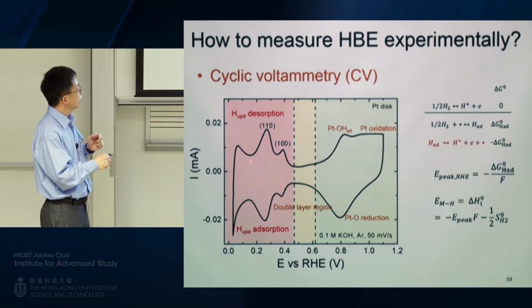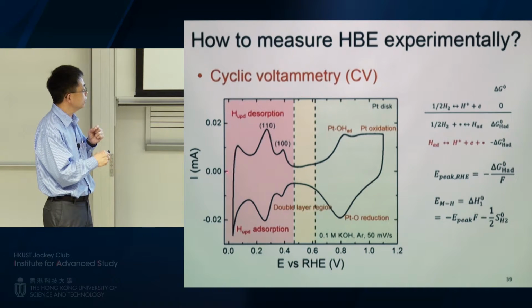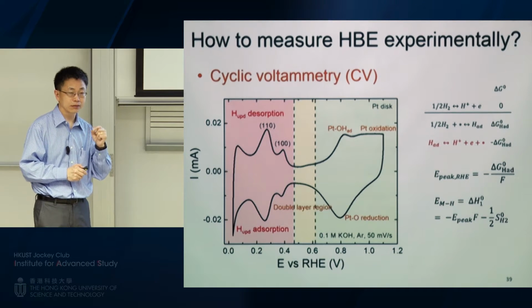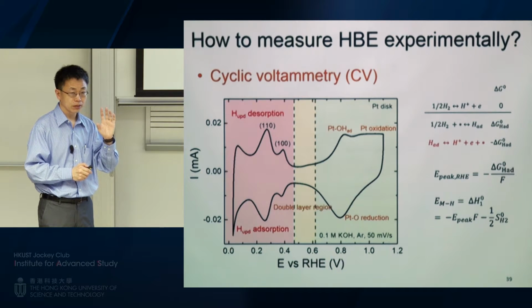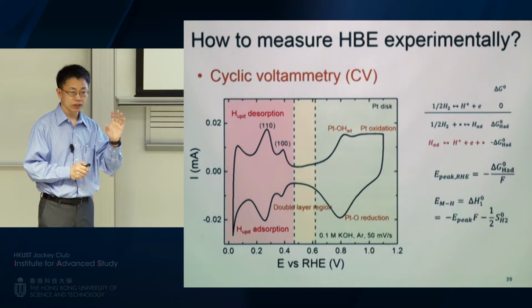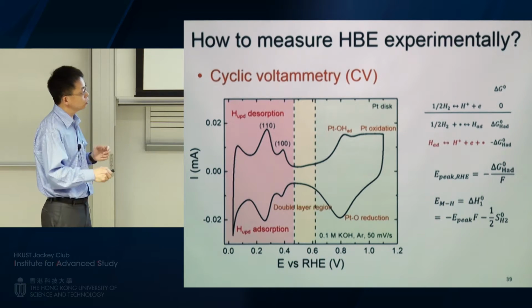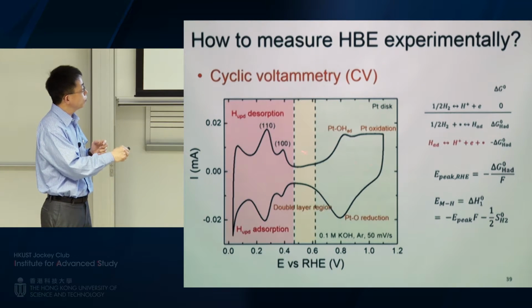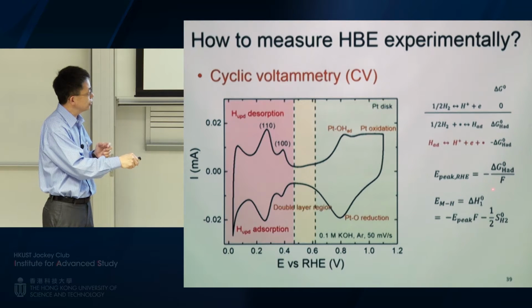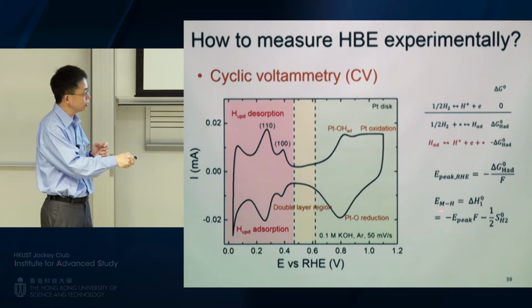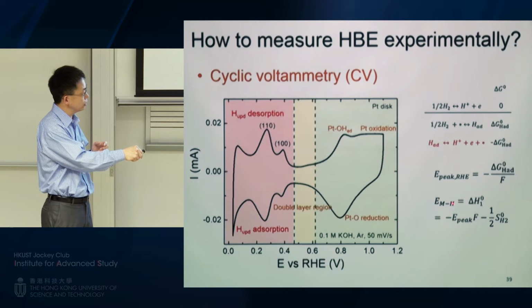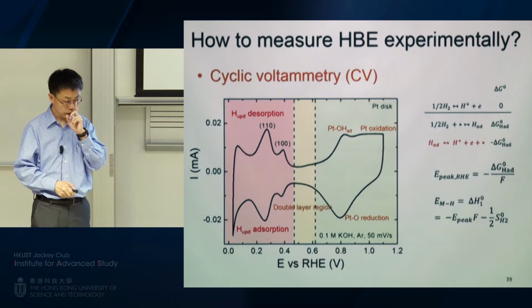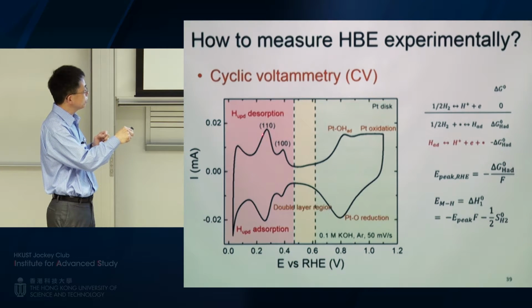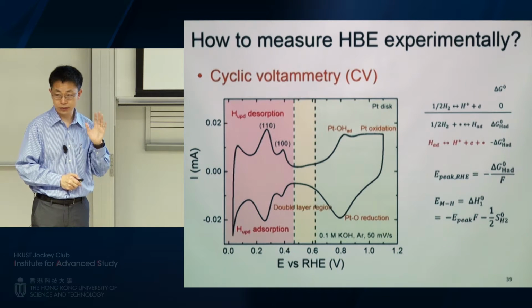What I want to say is, it has been known for a long, long time in the electrochemistry community that the peak position here is actually related to the hydrogen binding energy. So this is known. But there was no rigorous derivation based on thermodynamics and adsorption. So we did that. It turns out the peak position is indeed related to the hydrogen binding energy by a formula like this. So there's just an entropy difference. So you can see the peak position is literally the hydrogen binding energy. So what this tells us is, if you just measure the peak position, you already have the hydrogen binding energy. So this is very important.